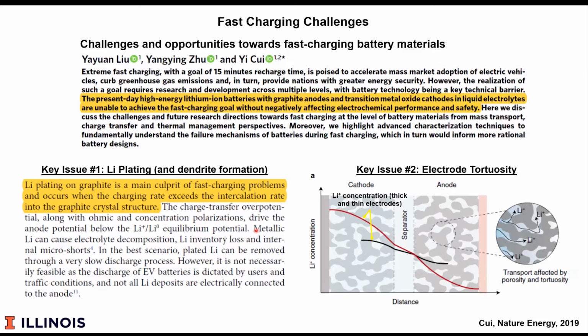The second key issue that I see, and related to this, is electrode tortuosity. Conventional cathodes are, say, 50 to 100 microns thick. However, they have tortuosities that may be on the order of 2 to 5, maybe even a little bit more. So if you have a 100 micron thick electrode with a tortuosity of 5, that means that the average path length for the lithium to get from the top to the bottom is going to be 500 microns. And that exacerbates all of the problems of the kinetics.